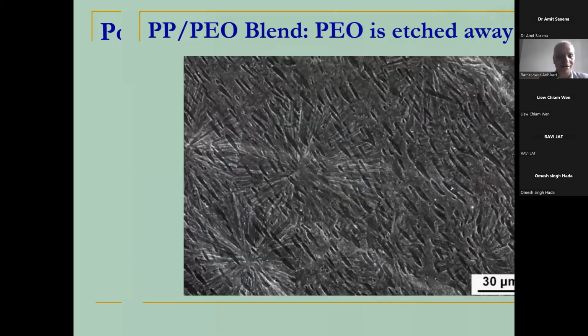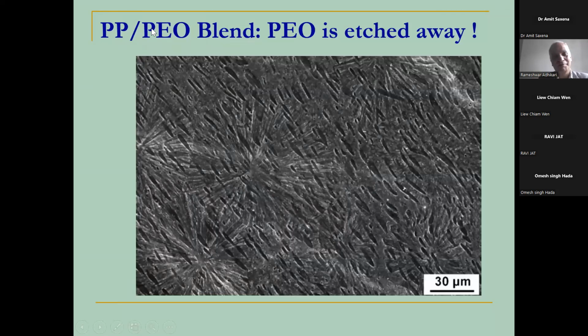And if we have a blend of polypropylene with much more flexible polyethylene oxide, which is not very well bound to polypropylene, they are removed by etching. So you have produced this kind of empty spaces. You see that. And if you look from the distance, you can see that the spherulite structures of polypropylene are still there. This is a spherulite. Another spherulite. Boundary is there. And PEO is etched away. I don't have many more examples now.